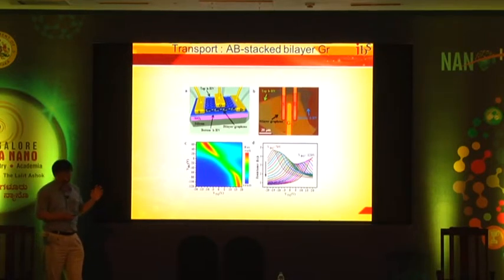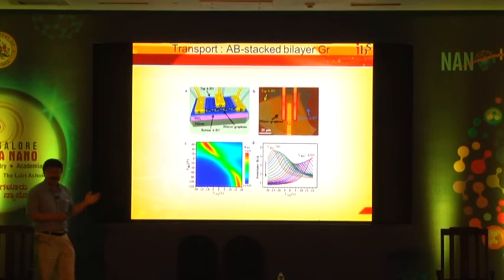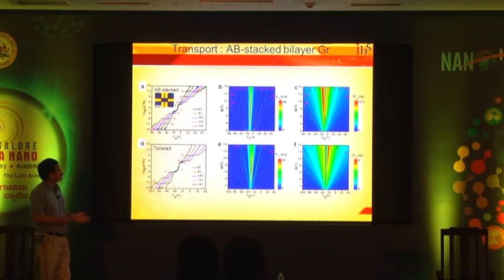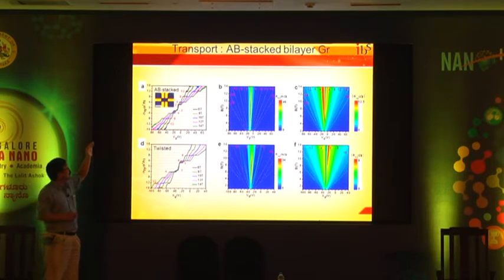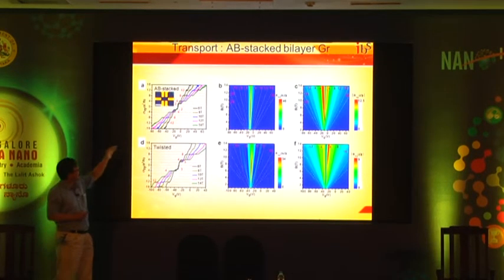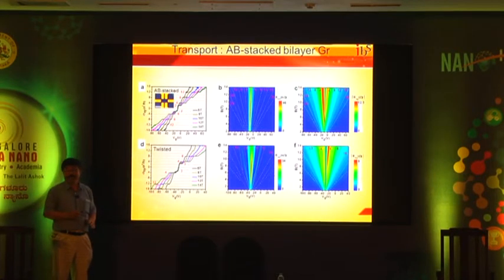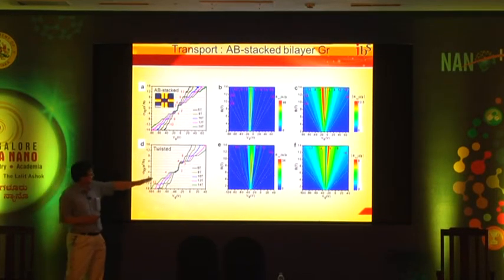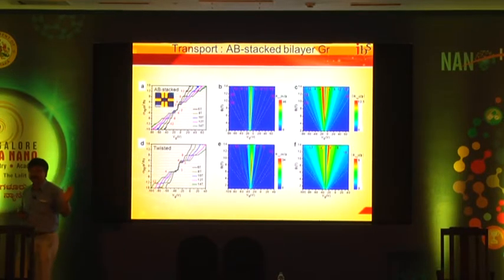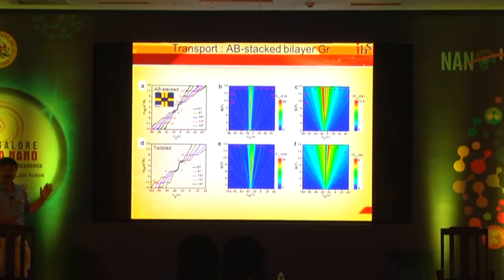But still, it's a very sensitive issue whether you truly have AB stacking order. So you have to go into something more serious. In this case, we do observe the quantum Hall effect. You can see clear discretized Landau levels, and then you can simply identify them. And if you twist by even less than 1 degree, you can clearly see different Landau levels up here. So this indicates our method works, even from an electronic point of view.